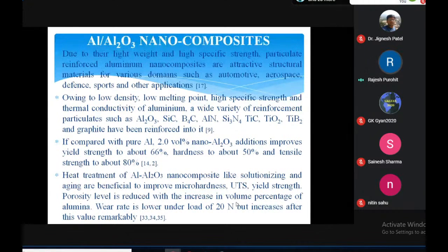Compared with pure aluminum, 2 volume% nano alumina addition improves yield strength by about 66%, hardness by about 50%, and tensile strength by about 80%. Heat treatment of the aluminum with aluminum oxide nano-composite, like solutionizing and aging, is beneficial to improve the micro-hardness, UTS, and yield strength. Porosity level is reduced with the increase in volume percentage of alumina.